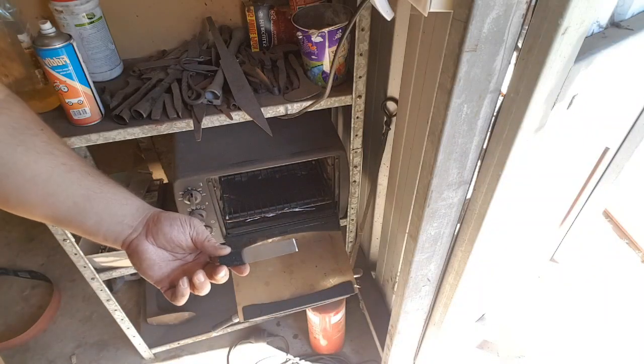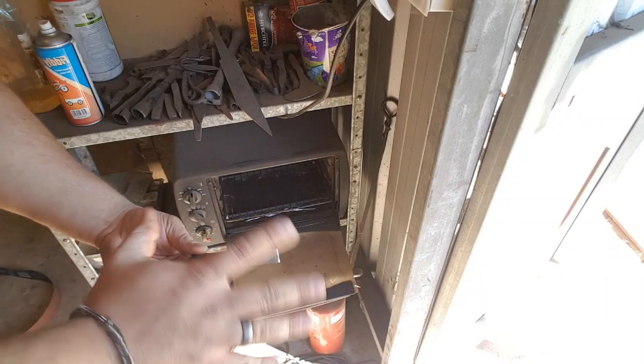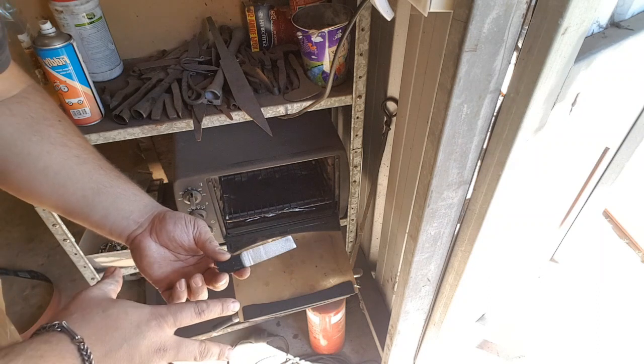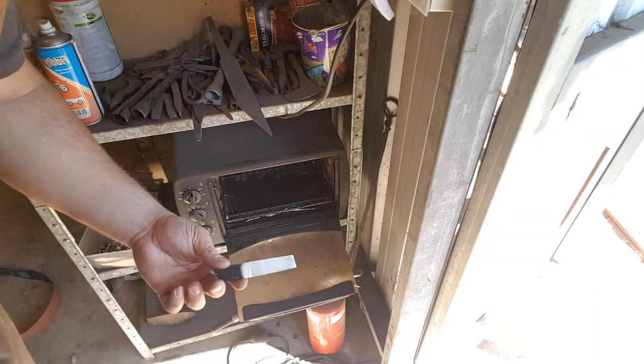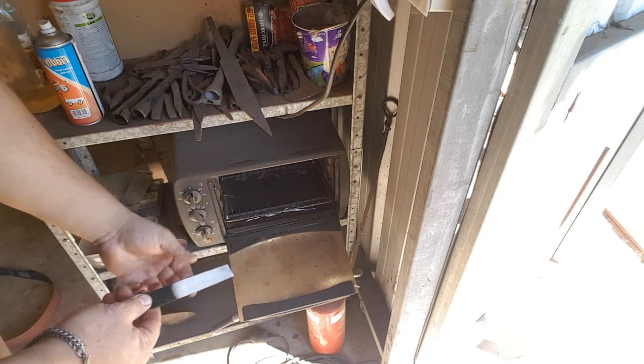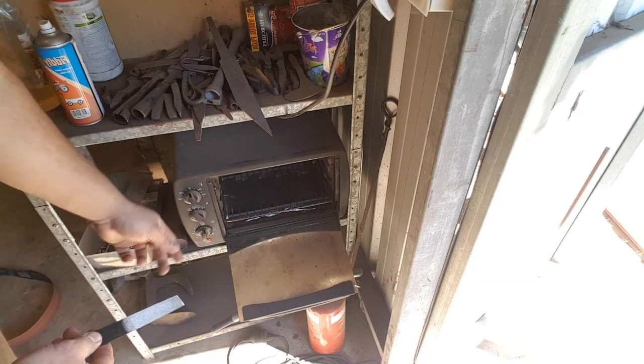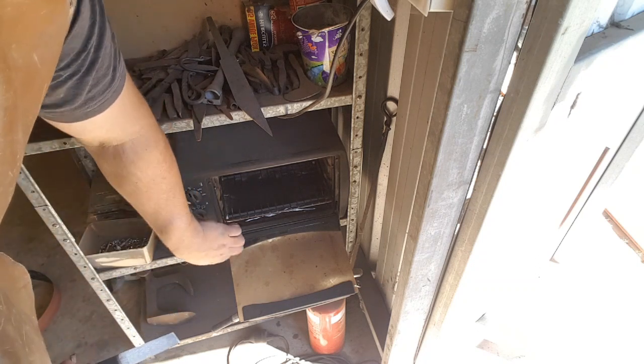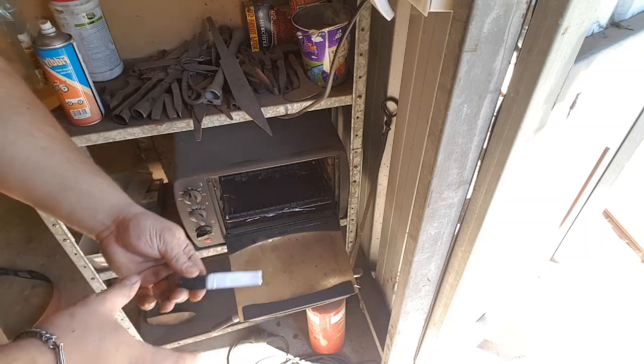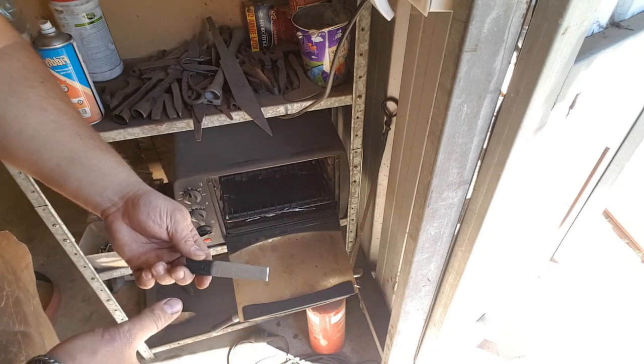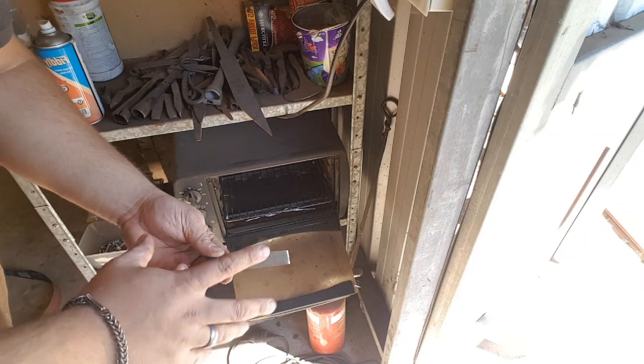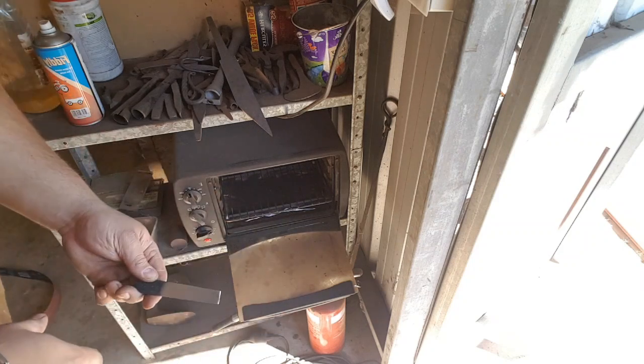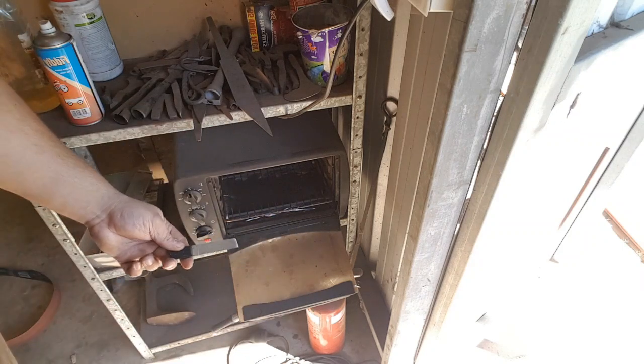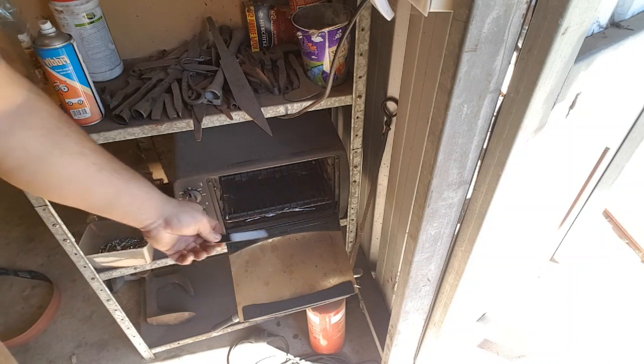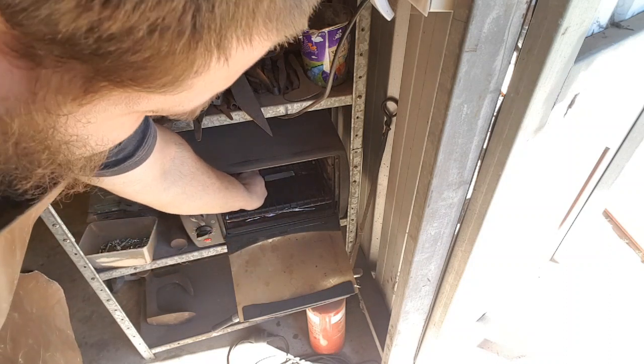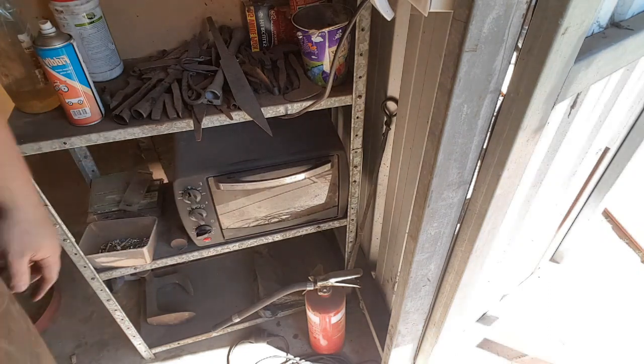Alright, so I've cleaned the steel. I've only cleaned a portion of it. I don't need to worry about too much because we're just going to show the colors on this. And what we're going to do is set the oven to about 180 degrees, and we're going to put it on for an hour. Normally I would do a 2-hour cycle and then cool it to room temperature and then another 2-hour cycle. The time at temperature does actually have an effect, but we won't get into that today. And basically all I'm going to do is set it in the oven, nice and even, and close the door.